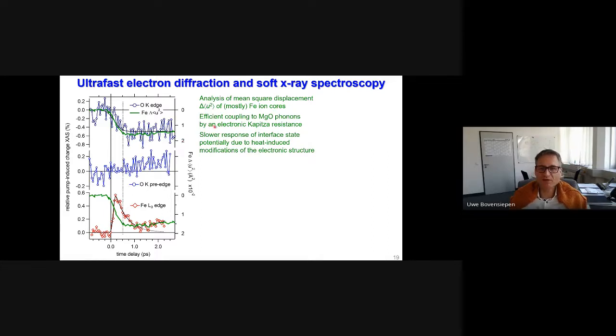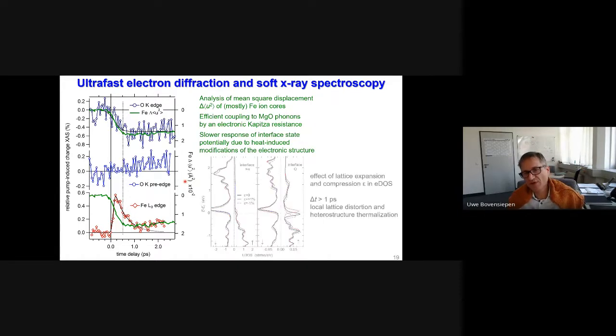And we explain this by a so-called electronic Kapitsa resistance, where there's electron-phonon scattering occurring right at the interface. Now, I would also make a comment here to the slower response of the interface state. So this is this dynamics that is clearly slower here in the pre-edge region. So here we have a scenario that is based on heat-induced modifications of the electronic structure and excitation of acoustic phonons. So remember, we probe here a specific feature in the vicinity of the Fermi level at the interface of oxygen. And if we allow for certain changes in the expansion or compression of the lattice, this electronic feature will change its energy, which explains then that this is a feature that is sensitive to lattice expansion or compression.